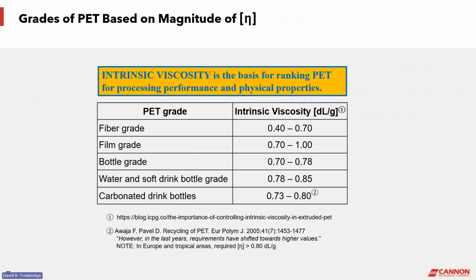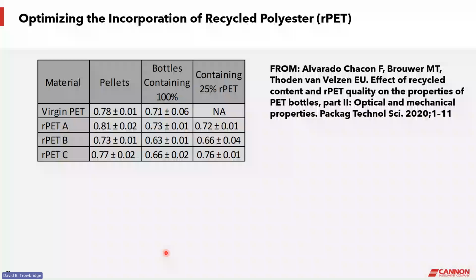Here's an example of PET, but it was a virgin PET, and then some recycled PET that was blended with it. And again, intrinsic viscosity was used as a criteria to evaluate how the processing impacted the polymer materials. So here they measured the intrinsic viscosity of the pellets of a virgin PET. I got a value of 0.78. And be mindful of the uncertainties that they're reporting for this intrinsic viscosity, very tight.